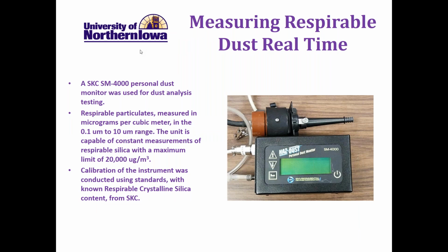How do we measure the respirable dust? Well, we looked at measuring real-time results. Anytime we move sand, whether it's off the end of a conveyor belt, whether it's off the end of a continuous mixer, we see dust being generated. We want to be able to measure that dust when we move the sand. So we are looking at respirable particles, measured in micrograms per cubic meter, in the range of 0.1 micrometer to 10 micrometer. This device was able to measure up to 20,000 micrograms per cubic meter, much over the OSHA standard PEL.